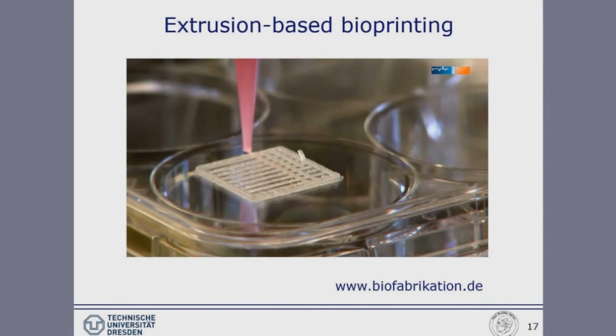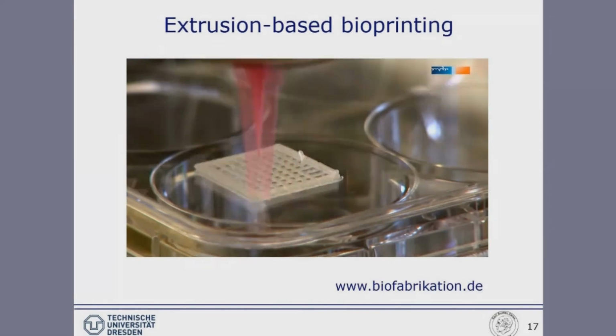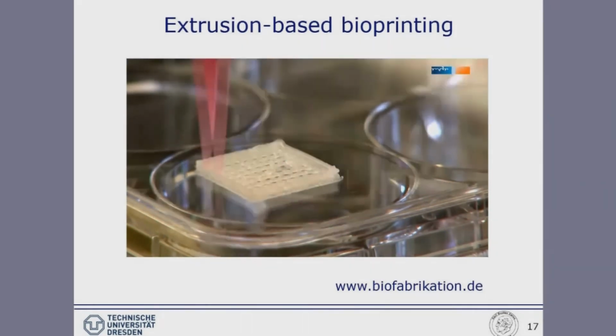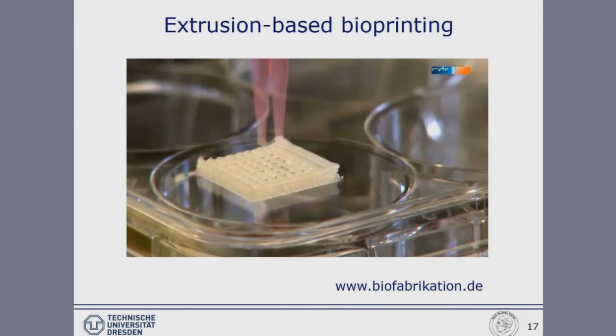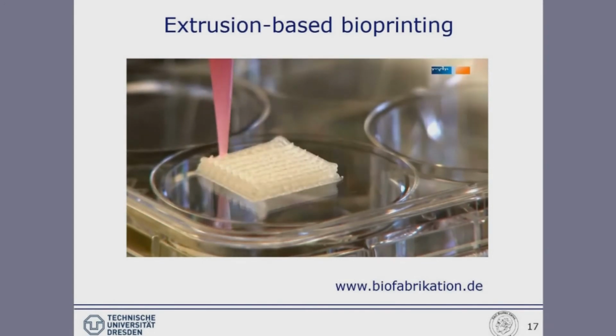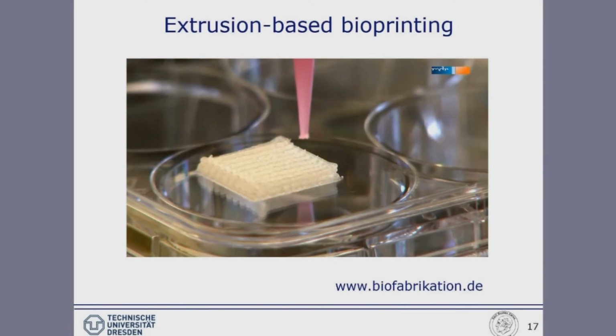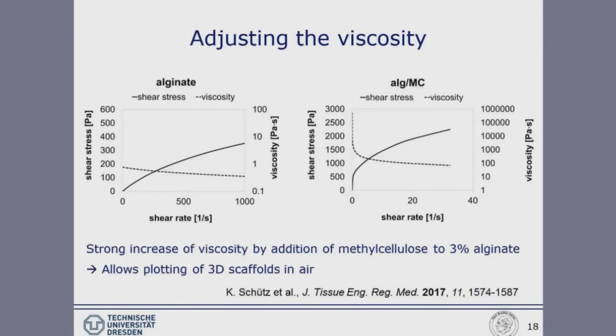So this is how we do this in our lab with the GeSiM printers we are using. This is now, of course, time-lapse. And as you see, we can print in air as the viscosity of the material is suitable for this. So we don't need any stabilizing liquid, and we can do this even with, for example, a 50-layer scaffold you have seen on the photograph before. The reason for this is, of course, the significantly altered viscosity of the blend in contrast to the pure alginate.